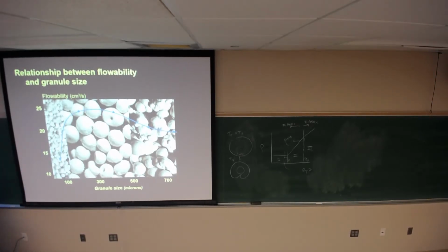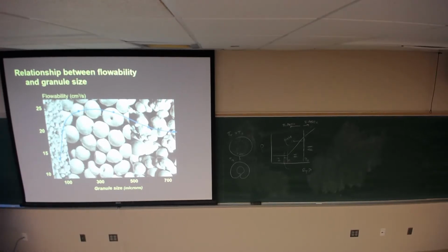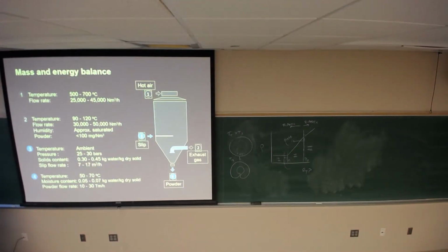But it's very likely that they all do. This one here too has. You can see it's not uniform, but that's what you end up with, that non-uniformity. That hole is extremely difficult to get rid of. Do they care? No. They do, but they don't. They live with it. The reason you get the hole is because they drive up the solids concentration in that